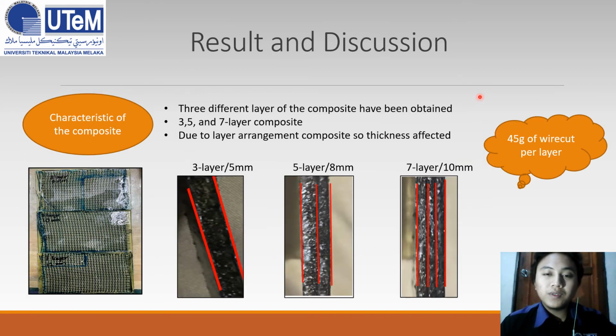Okay. After we have gone through our experimental procedure, we proceed to our results and discussion. For the result of the fabrication of the composite, three different layers of composite have been obtained: 3, 5 and 7 layers. Due to the layer arrangement, the composite thickness is affected by the number of layers. For example, as you can see in this picture, the 3-layer composite has a thickness of 5 mm, while the 5-layer composite is 8 mm, and the 7-layer composite is 10 mm.